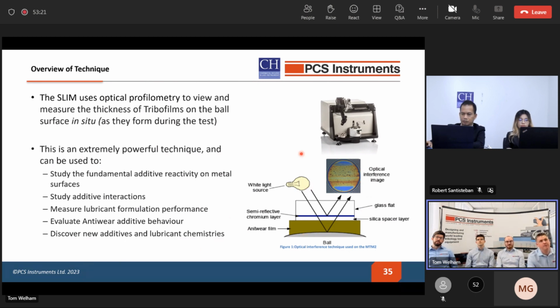So the system works by bouncing a white light off a semi-reflective disc. Part of the light is reflected directly back. Part of it goes through the contact and reflects off the steel ball, and when the light recombines, we have constructive interference at different frequencies depending on the thickness of the anti-wear film that's formed on the surface.